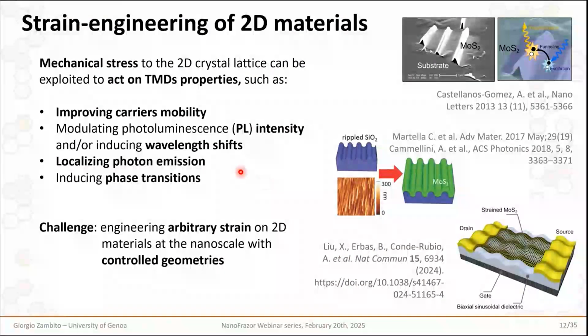Strain engineering is a term that is generally used to identify this way of tailoring properties of materials in general, and in this specific case, of two-dimensional materials. It has been proven that when you apply a mechanical stress to the crystal lattice, of course, you change the properties that arise from the presence of a crystal lattice. For example, it has been shown that it can induce an improvement in carrier mobility in transistor configuration. You can modulate photoluminescence intensity, induce wavelength shift, even localize photon emission, or, for high degrees of strain, even induce semiconducting to metallic phase transitions.